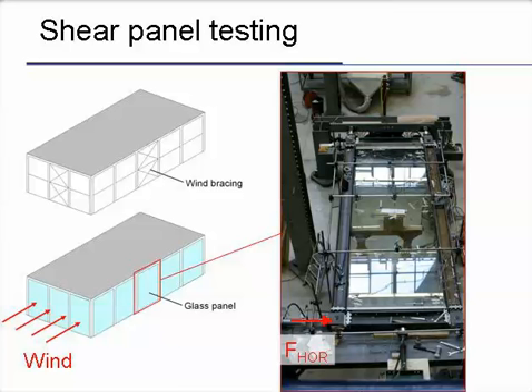And we are doing tests like this, where you put a horizontal force, and here you have a glass panel which has either linear or point support. And the idea, of course, is to go further and maybe to propose a complete structural system with glass and steel that can be sufficiently ductile to be used, and not anymore only use the glass for its stiffness and the frame around for its ductility. Together they can work.